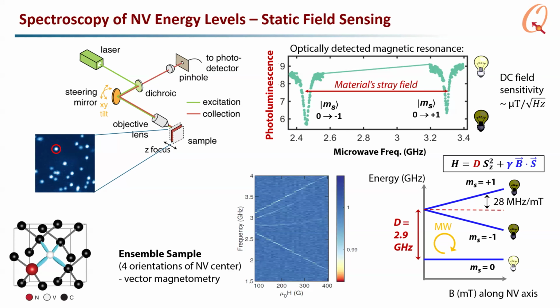Okay, so if we scan the magnetic field here, you actually see the Zeeman splitting of the NV center. There are two extra peaks here, and this data comes from an ensemble sample. You see that the NV center actually has 4 different orientations in the diamond lattice along the 111 directions. So 3 of the orientations are degenerate in this picture, and one of them is splitting linearly.